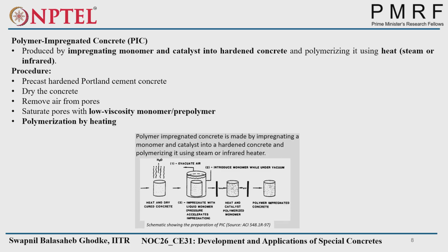High. Because we are filling all the pores with the monomer and catalyst, and that converts by polymerization. So with no pores available, no external hazardous factor or hazardous material will come into contact, go into the pores and affect the hardened properties. But in normal concrete, there will be a certain amount of voids available. If they are connected, they will create a permeability issue also.